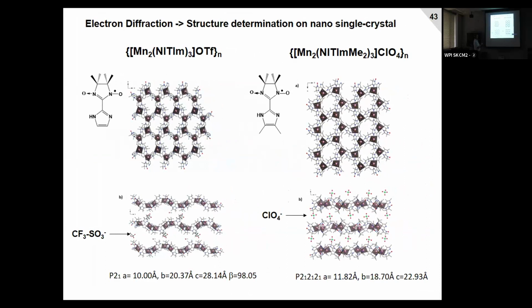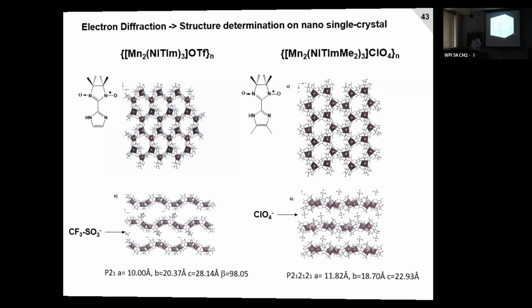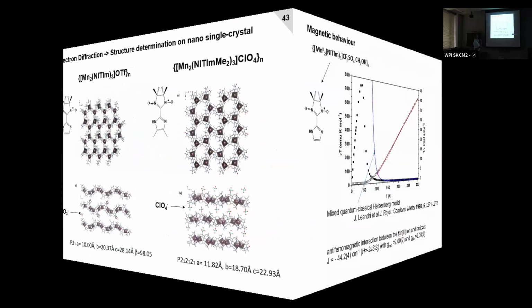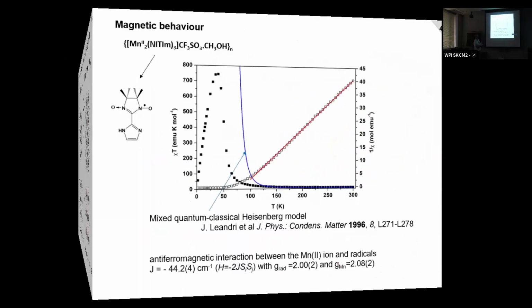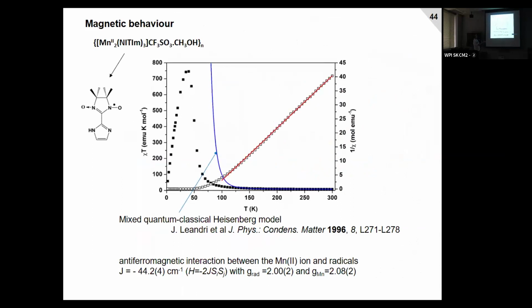You have to see that this structure has a corrugated shape. Why do we have this shape? We think it is because here we use the OTf-type anion, which has the SO3 group and the CF3 group. So there are different bonds between the layers that make this shape. And with perchlorate, we have an almost layered system. When we look at the magnetism, it's normal magnetism, a ferrimagnetic layer, and you have still here the layered structure.